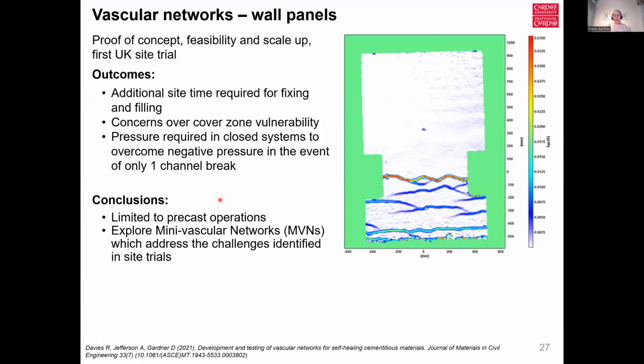So what was the outcome of the trial? Well, it was an interesting outcome. I wouldn't say that it was particularly successful because when there's a lot of reinforcement in an element, it's actually very difficult to separate the pre and post damage loading response and being able to attribute anything to the actual self-healing response and action. In our case, the sodium silicate was quite difficult.